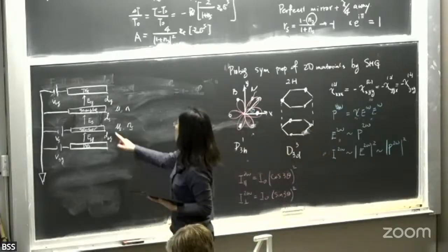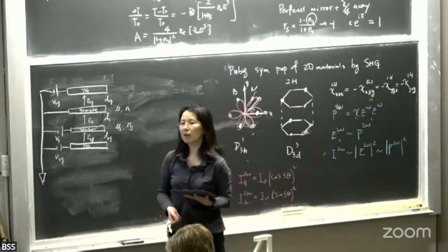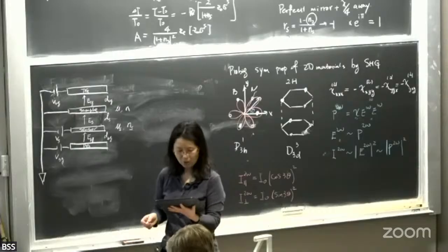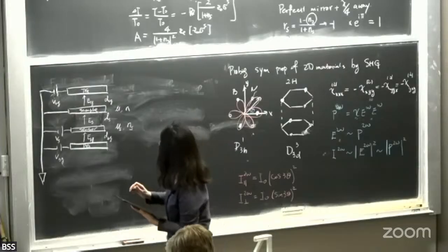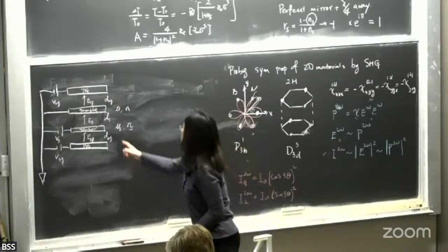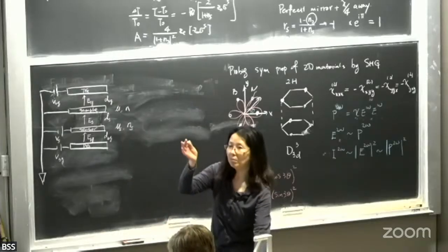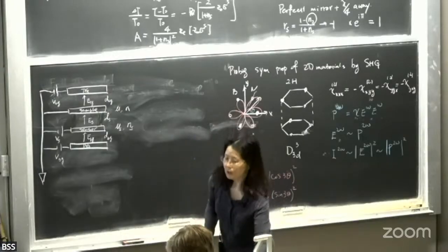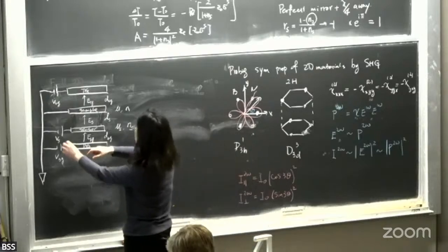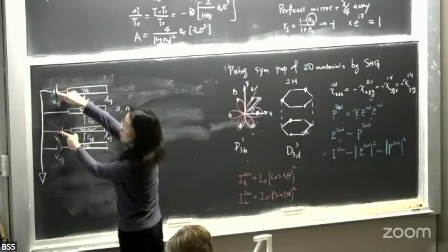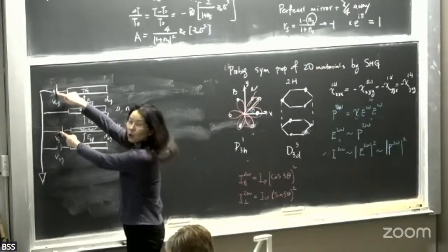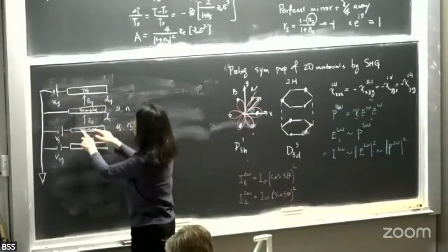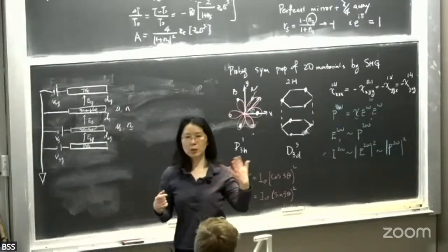So, you know, this sensor can be graphene, for electrical measurement. It can be a monolayer of semiconductor for optical measurements. So let's say you can set your sensor to some reference point. You know, you pick somewhere as your reference point. In the measurements, you can now change those two gates to control the density, also displacement in your sample, right? So once you do that, the sensor chemical potential will be shifted.